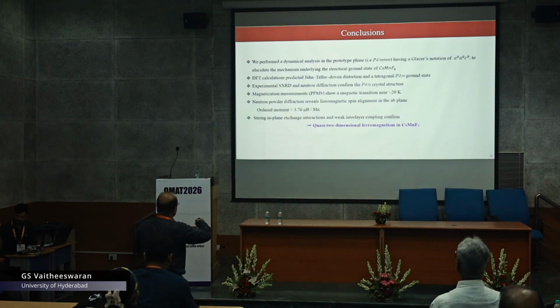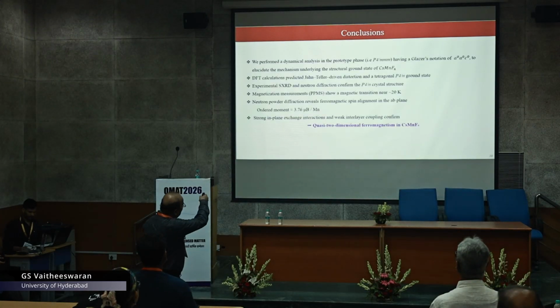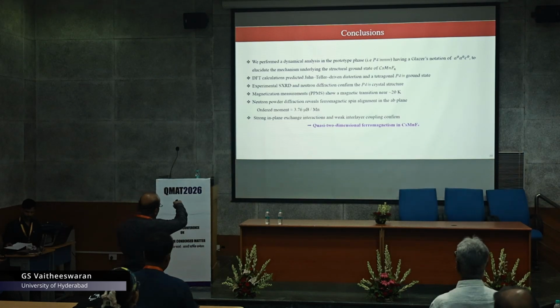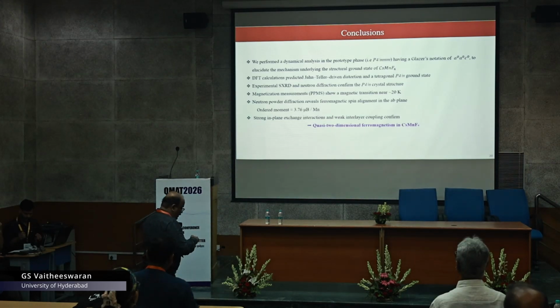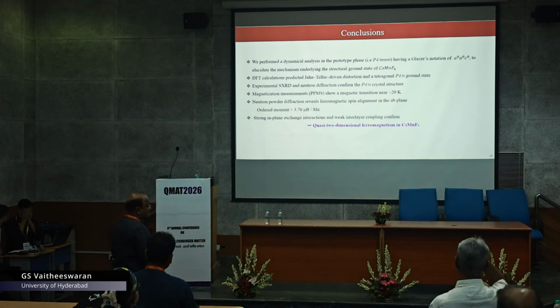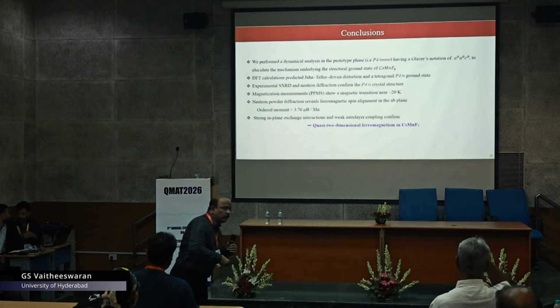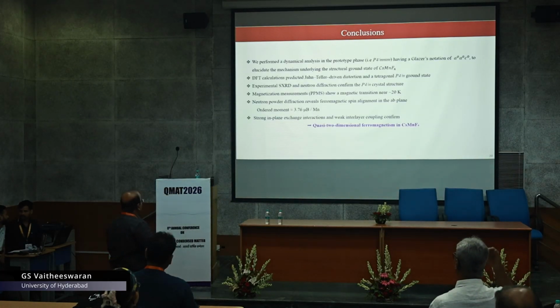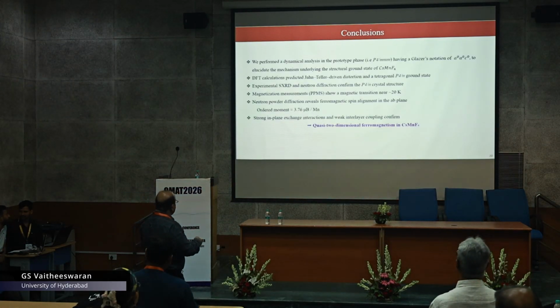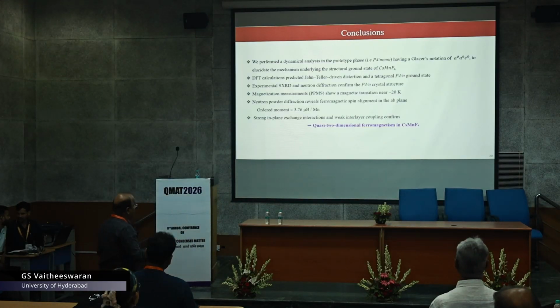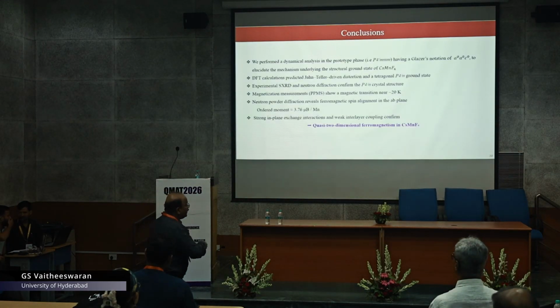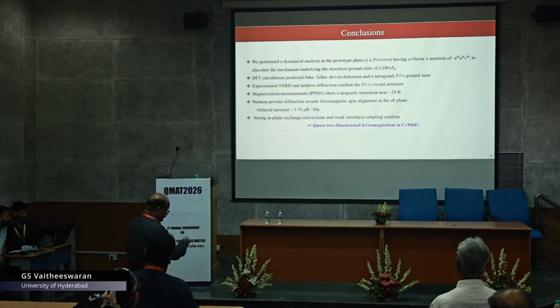And then this magnetization measurement shows a magnetic transition at 20 Kelvin, and the magnetic moment observed from the neutron is 3.76, whereas our theory is slightly tending to overestimate the moment. And then we confirm a strong in-plane exchange interaction and weak interlayer coupling, which confirms the quasi two-dimensional nature of the system.